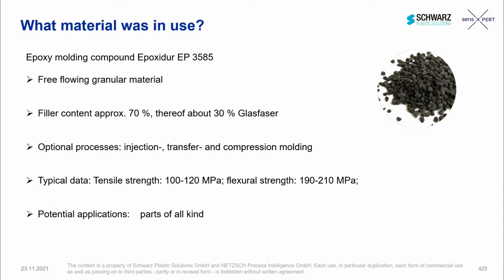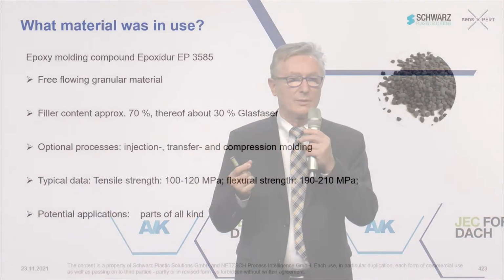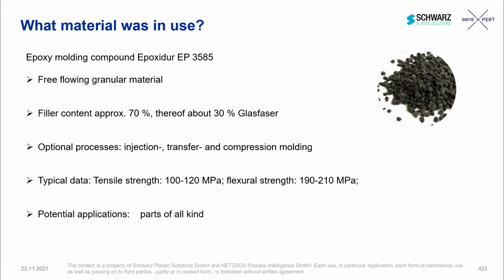In that particular case, we were using a granular material from the material maker Raschig in Ludwigshafen called Epoxydur EP3585. That material will be used, for instance, for encapsulation or for just single parts which are molded. And you can use compression molding, transfer molding, and injection molding processes. It's a material which is pretty stiff compared to thermoplastic materials. It has a filler content of about 70%. So, and that's the surprising thing compared to thermoplastic materials. The filler content is much higher. Therefore, the resin or the polymer content is fairly low, and still the influence is extremely high on the behavior.